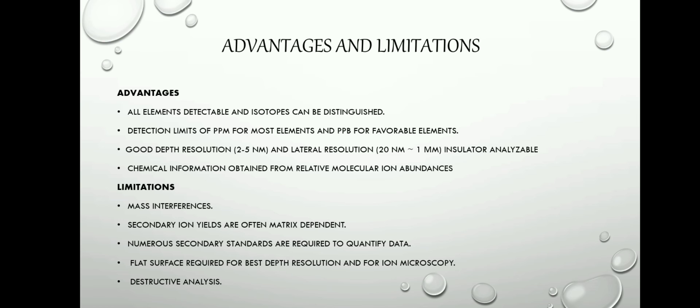Talking about the advantages and limitations. Advantages: all elements are detectable and isotopes can be distinguished; detection limits of ppm for most elements and ppb for favorable elements; good depth resolution of 2 to 5 nanometers; lateral resolution of 20 nanometers to 1 micrometer; insulators are analyzable; chemical information obtained from relative molecular ion abundance.